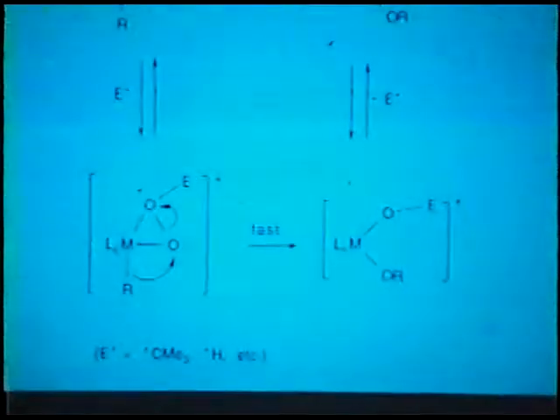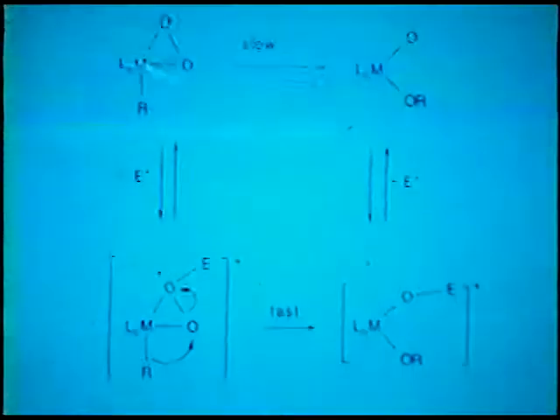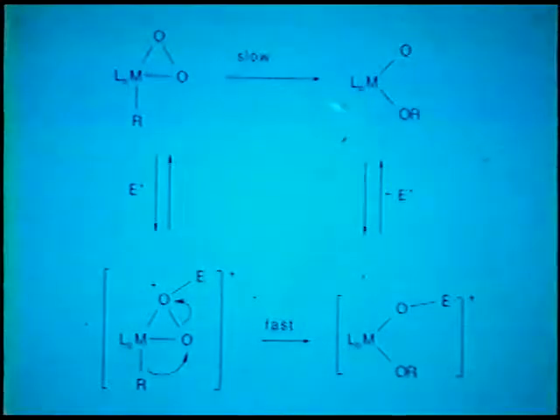Indeed, we have found other examples that fit the same scheme, where we now think that alkyl migration to peroxide oxygen is slow in the absence of electrophilic promoters. And the function of the electrophilic promoter is to encourage alkyl migration in a heterolytic sense, that is, into the sigma star orbital of the OO bond here. And that would, of course, imply that electrophiles would encourage that pair of electrons to heterolyze towards the positively charged oxygen, and then we can close the catalytic loop. We see terrific acceleration of some of these processes by added electrophiles.